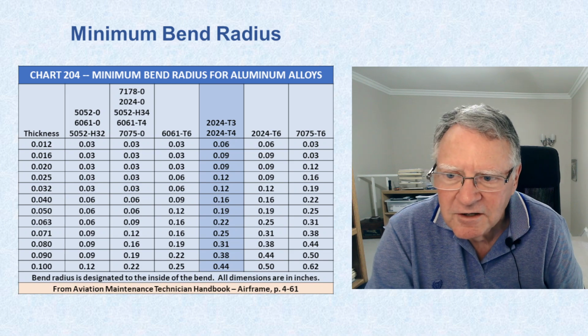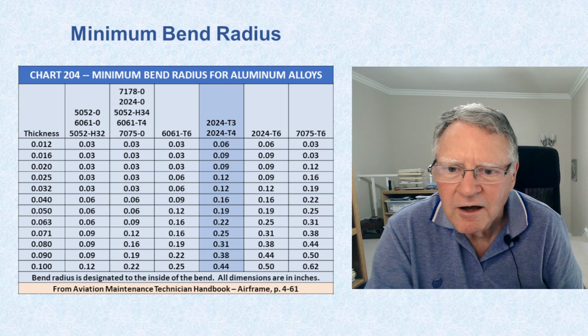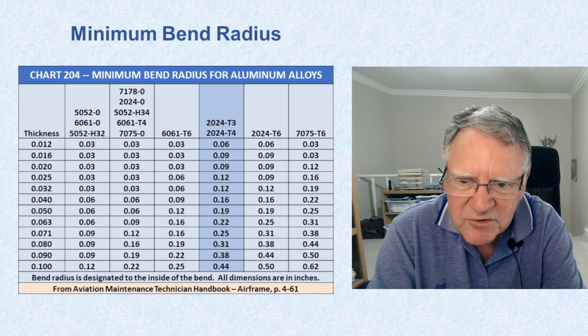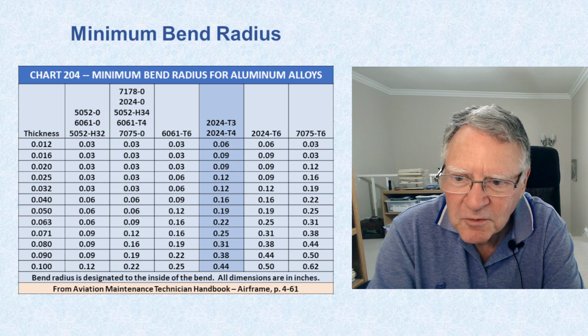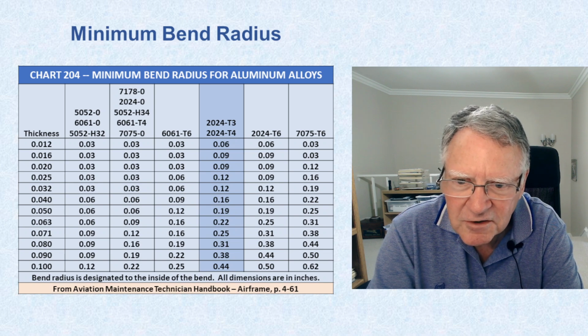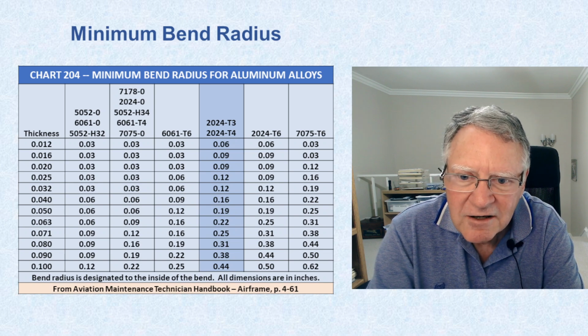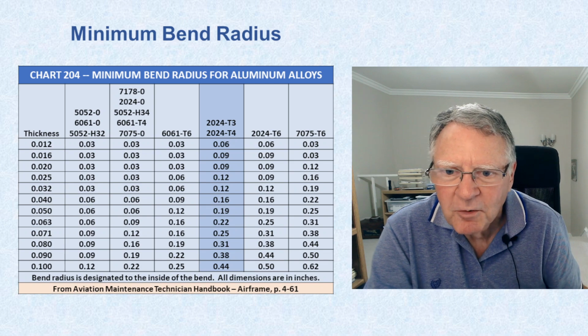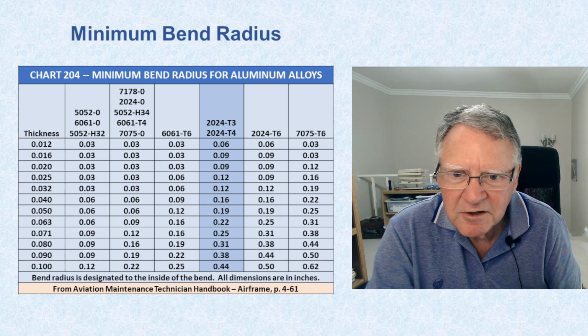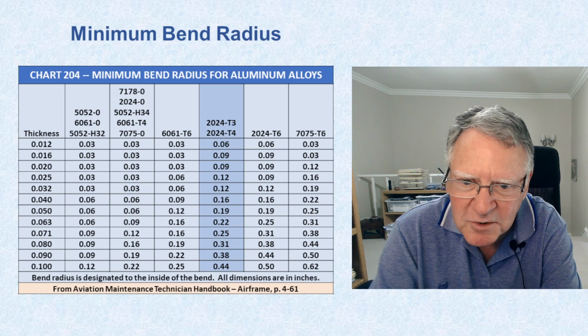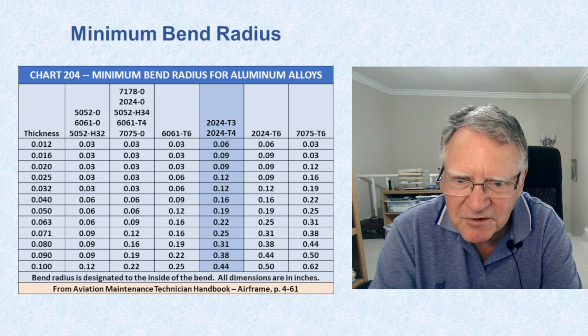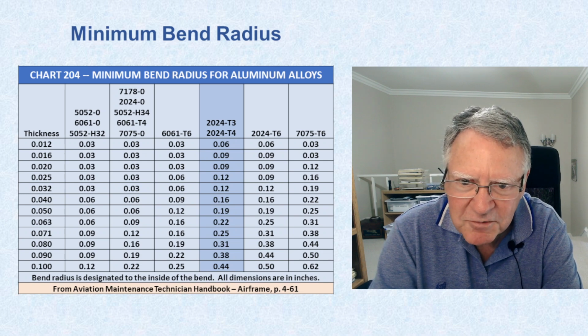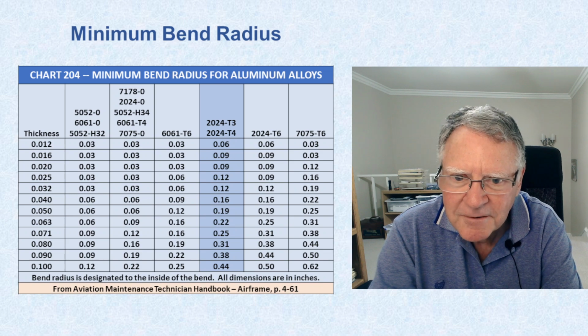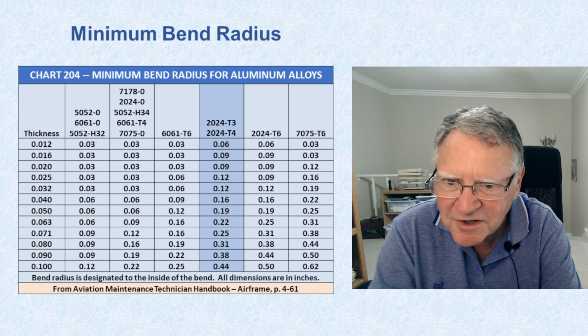If you look at the 2024, it is 0.16 inches. So the bend radius has gotten significantly larger. And if you keep on going and you look at, say, the last column here, the 7075 alloy, which is either the hardest of the aluminum alloys or close to it, it has an even larger bend radius. Now we're up to about 0.22 inches. It's almost a quarter of an inch.